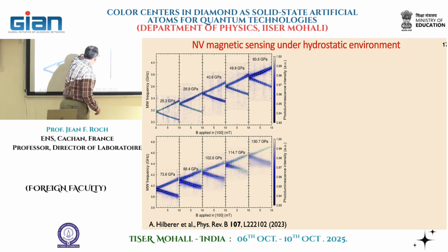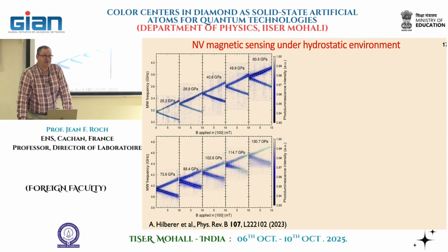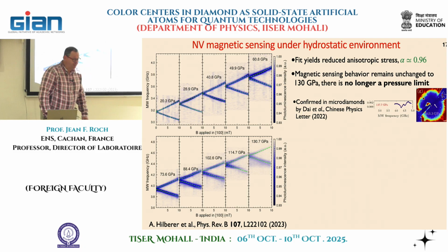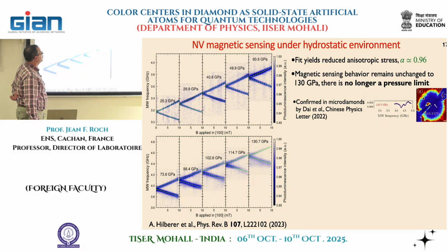It decreases on this branch, but the decrease is simply due to the fact that our microwave excitation was not efficient above 4 gigahertz, and that was a practical limit, but now we've been able to purchase new equipment to get contrast increase at those pressure ranges. And the fit gives us a value which is close to unity, saying indeed that we are close to hydrostatic conditions. So we can now have a method to maintain magnetic sensing behavior unchanged up to 130 gigapascal. So it's no longer a limit if we want to explore the superconductivity of superhydrides.